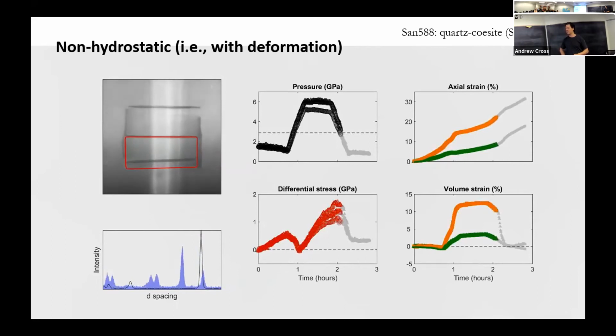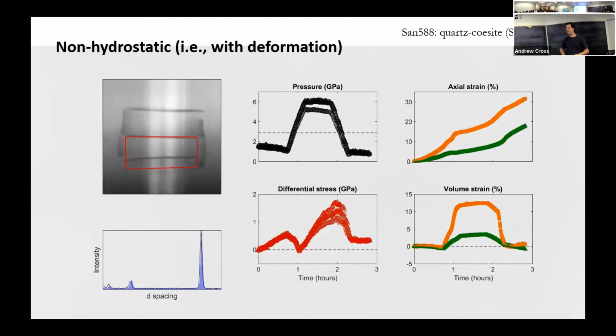We're going to decrease to our pressure ramp down. And again, we're going to see the stress drop. It's not going to go all the way back to zero. Instead, it's pretty much just going to go straight to steady state back in quartz. And the stress in quartz at the end is slightly lower than it was beforehand. Basically, that just corresponds with some grain size reduction that you get through the phase transition. The volume strain story is pretty straightforward. You get 10%-ish shortening from both the transformation itself and from the fact that you're just increasing pressure and pushing those atoms together, and then you recover your initial volume.